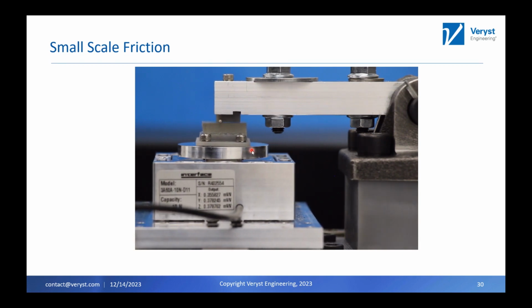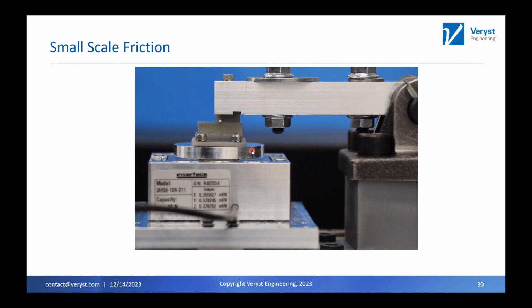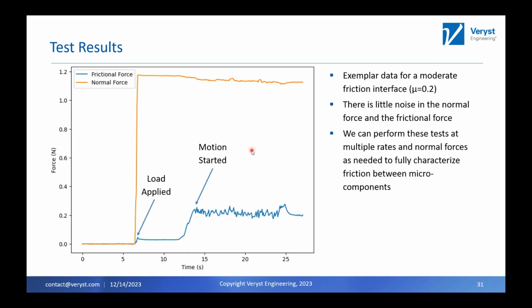So Sean, the test looks good, but what does my data look like? So this is a plot of the force from one of these friction tests, and the orange line shows the normal force, and the blue line shows the frictional force. So I've tried to point out here what's going on. We start the recording, and then we take that lever arm and put it down in contact to apply the normal load, and that's this jump. So we've got a normal load here of, we'll call it, 1.2 newtons.